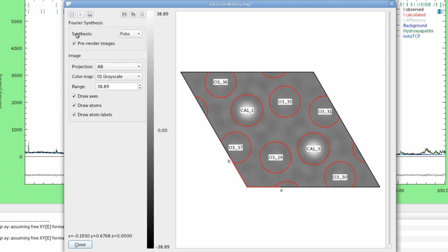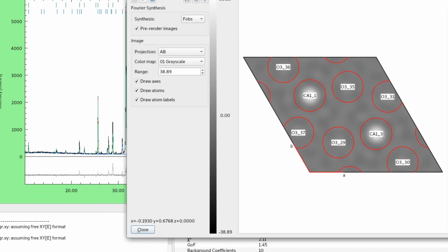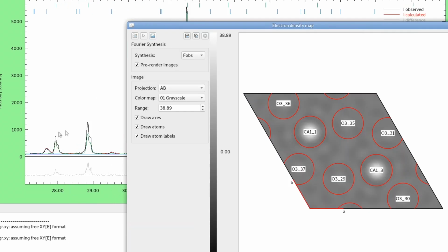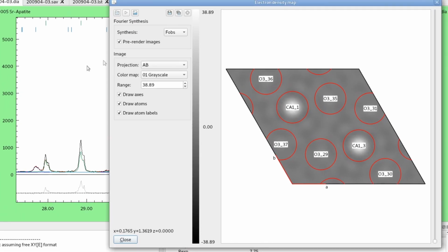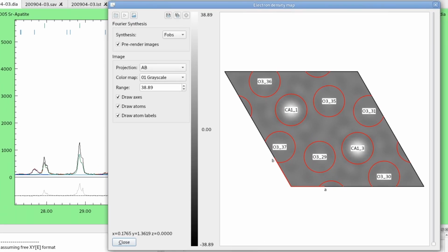A very important parameter for the Fourier synthesis is this box, the synthesis box up here. Now we have selected FOBS, which means that we are using the observed structure factors to reconstruct the electron densities. So if we look at the diffraction pattern, especially where we find mismatches, so here where we have two peaks with intensity mismatches between observed and calculated intensities, we have now used the observed ones, the measured intensities, to reconstruct